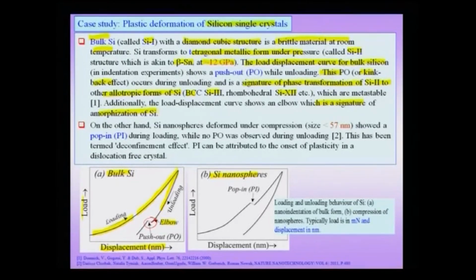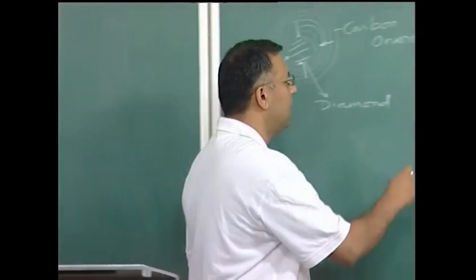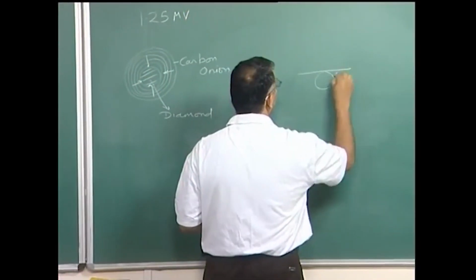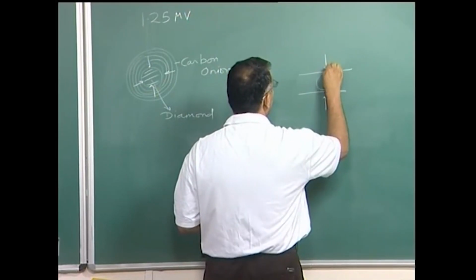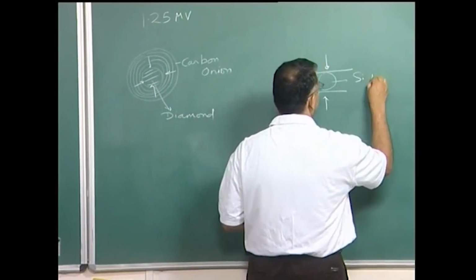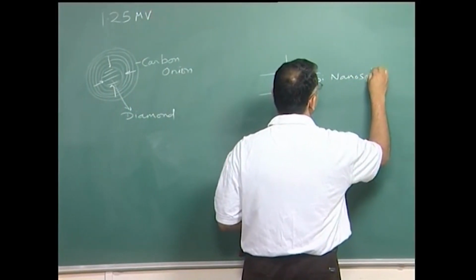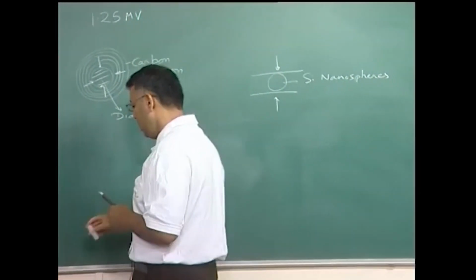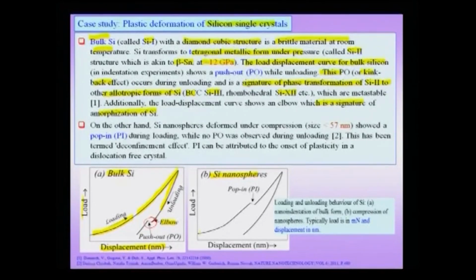Now, compare this bulk silicon indentation experiment, which is a deformation experiment, with the deformation of silicon nanospheres. What I am doing in the second case is taking silicon nanospheres and doing a compression experiment on them. In that case, you observe that the loading part of the curve and also the unloading part show a slight difference. In the loading part, you observe something known as a pop-in phenomenon, and these nanospheres had a size of about 57 nanometers or smaller.